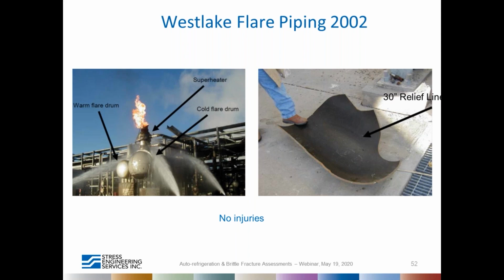Once the flaring of ethylene began in this particular scenario, the cold flare drum overhead line experienced low temperature at some point, and that low temperature was not recognized due to faulty instrumentation. Now, this resulted in the failure, but the investigations done on the failed material indicated that the material did not meet the required Charpy energy, and the failure was at an elbow, and elbows are typically highly stressed locations in a piping system.